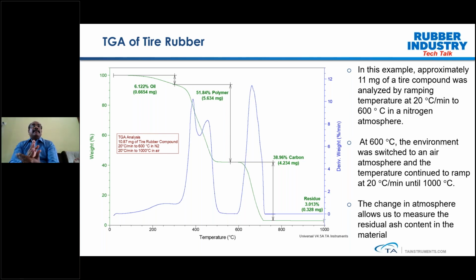Once the temperature reaches 600 degrees, that's when we do a gas switching. We switch from nitrogen to air, which further burns up the carbon black present in the polymer compound, and then immediately we can see the weight change corresponding to the carbon black decomposition, which accounts for 38.96% in this particular case. And finally, what we see is the residue and the ash content, due to the presence of filler content, which is 3.013%. So now you can see from this analysis, we can clearly define the composition of the polymeric material.